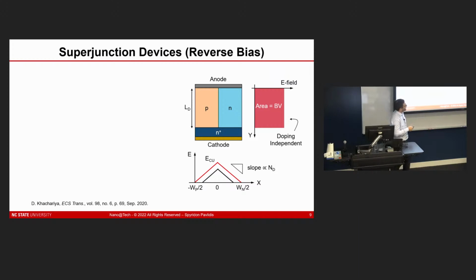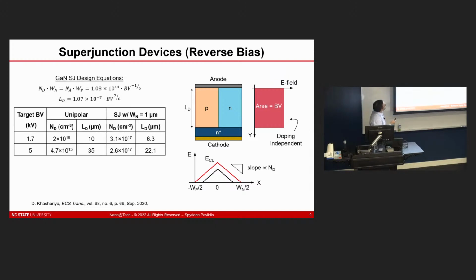So vertically, there's basically a doping independence, and it's laterally now that you start to see that triangular shape come out, where now doping and width of those stripes, these WP and WN layer parameters, become very, very important. So we're kind of flipping this structure over a little bit in terms of what we have to think about with doping requirements. And we did a lot of analysis, and others have done this as well, to understand how these relationships work for gallium nitride. And these are some examples to kind of give you a very direct feeling of what the benefits are.